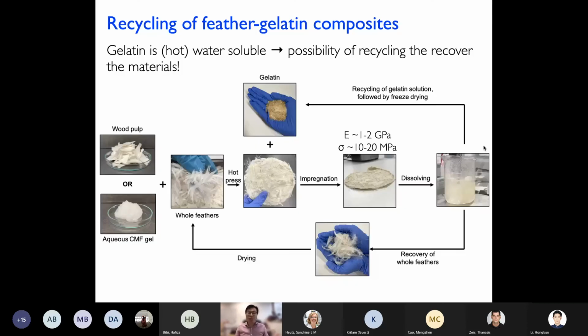What we did there was then impregnate these feathers with gelatin. You actually produce something of a decent mechanical performance, which we can use for an extended period of time, after which you would dissolve, recover your gelatin, recover your fibers, and you can start all over again. So there is a possibility of creating materials that you can use, dissolve, and you can make the preform again to your liking, allowing you to essentially close the loop, if you will.